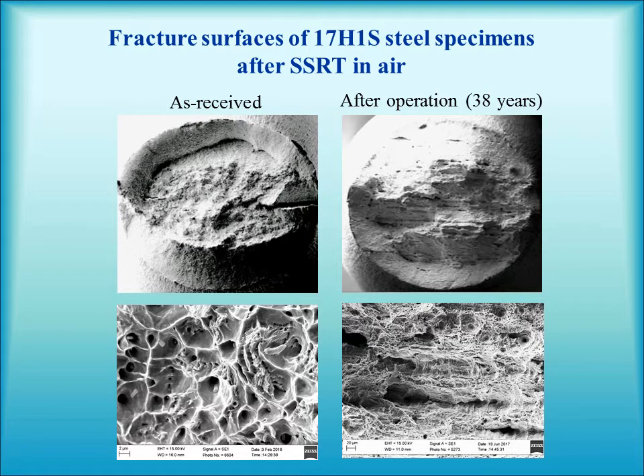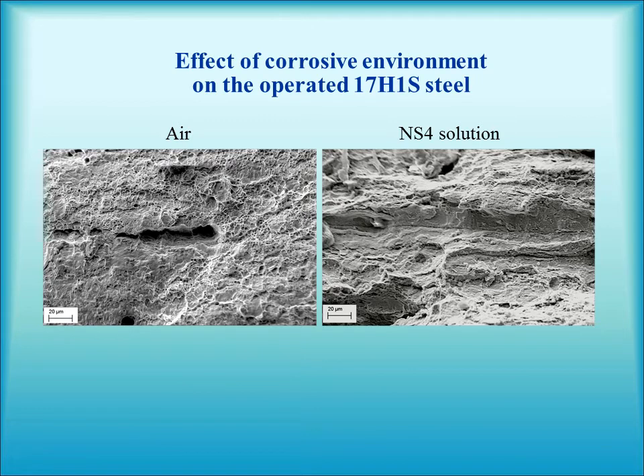Analyzing fracture surfaces of specimens after the tensile test, it is obvious that the effect of steel texture is more pronounced for the operated steel, even under a low magnification. Besides, for the operated steel, the effect of degradation is clearly revealed after the testing in the corrosive environment. Delamination after the testing in air is surrounded by a ductile relief consisted of dimples, whereas in the case of NS4 solution, delamination became the origin of brittle fracture in the form of transgranular cleavage. This trend maintained not only near the external surface of the specimens contacted with the corrosion environment, but also in the center of its cross-section. This indicates a possible occurrence of this delamination before the testing during steel operation, because of cohesion weakening between adjacent layers of ferrite and pearlite.